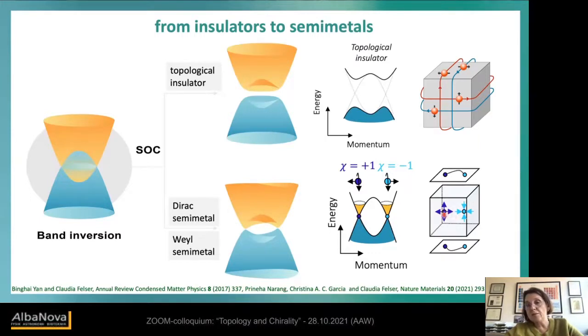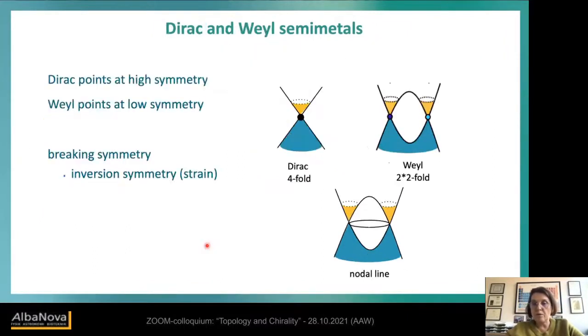So they are chiral, and the surface states connecting these Weyl points' projections on the surface are Fermi arcs. Because of this chirality, these Weyl points and the Weyl fermions became more attractive, I would say, than Dirac semimetals. But more or less, if you apply a magnetic field, what you do in a Hall measurement, a Dirac semimetal immediately turns into a Weyl semimetal, and therefore many Dirac semimetals show the same properties.